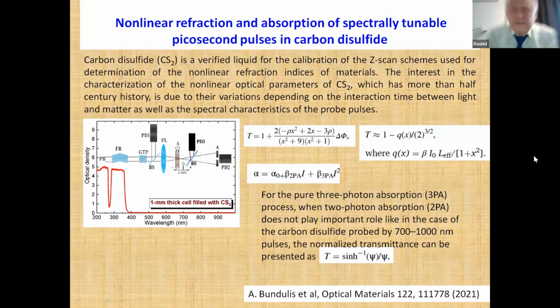Why is this material interesting for researchers? All nonlinear optical studies of materials are mostly calibrated using carbon disulfide. However, in most cases, they use the calibrated values only at 800 nanometers, which is the most useful laser wavelength in the case of femtosecond lasers, or 1064 nanometers, which is the wavelength of the YAG laser.